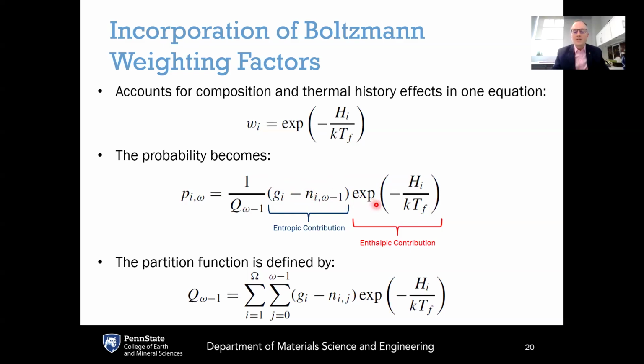And when you combine these together, you have the entropic contribution and the enthalpic contribution. And so you've got different relative weights. What largely governs the different weights between entropy and enthalpy is the fictive temperature. So if you've got fast cooling or a high fictive temperature, that favors entropy. A low fictive temperature favors energy or enthalpy.